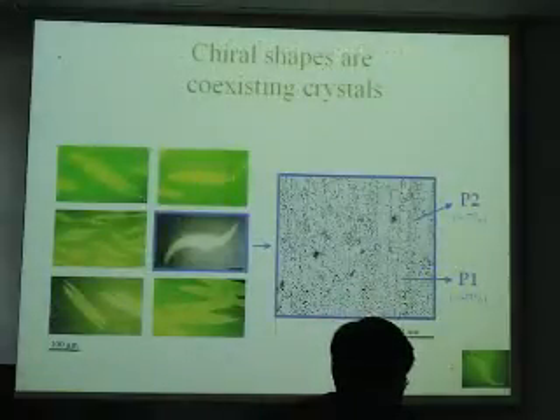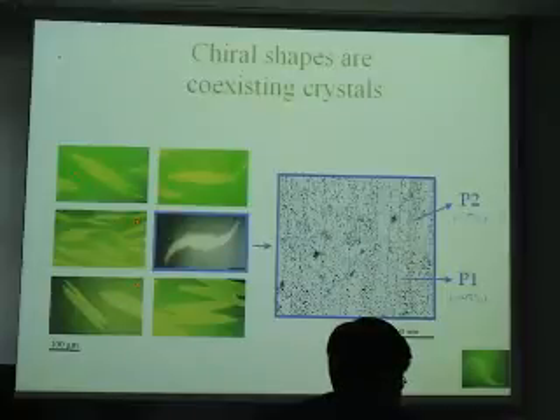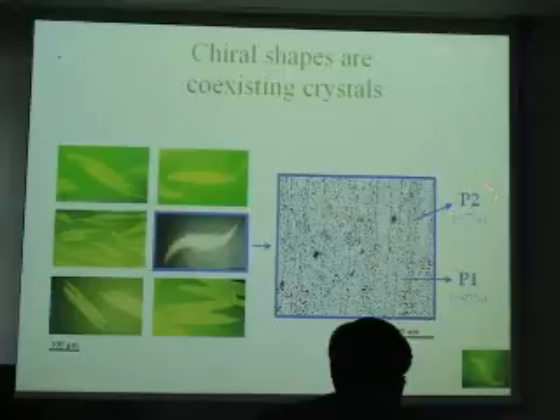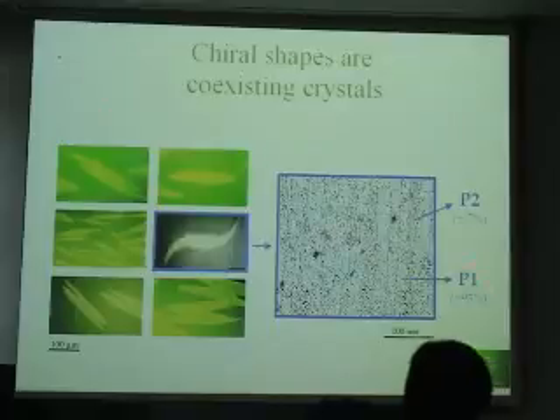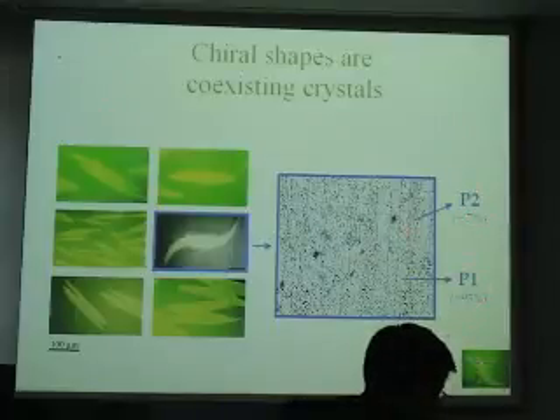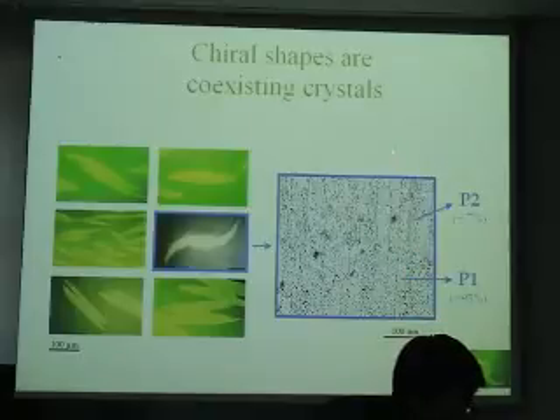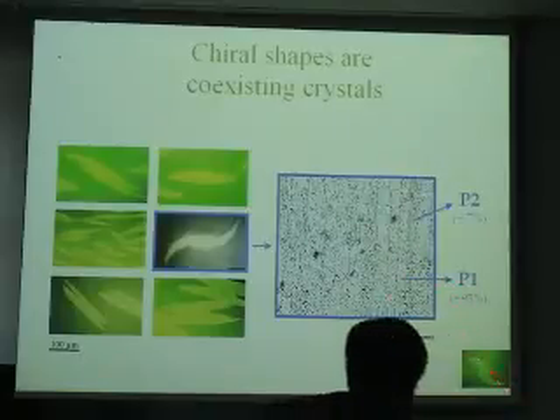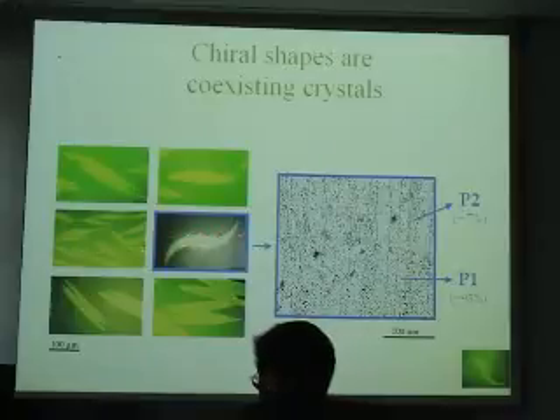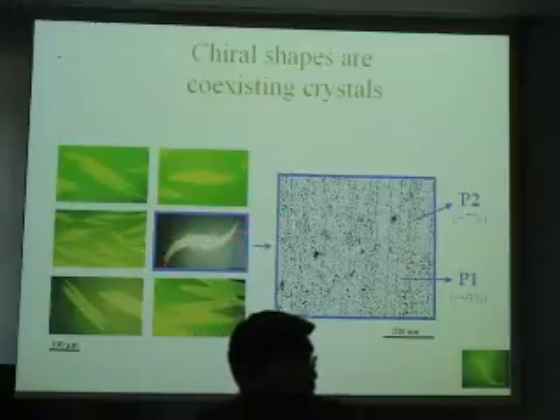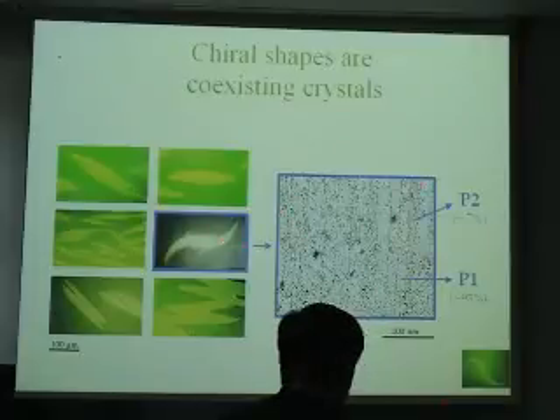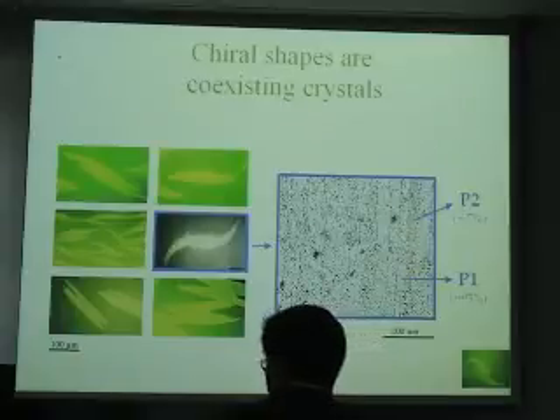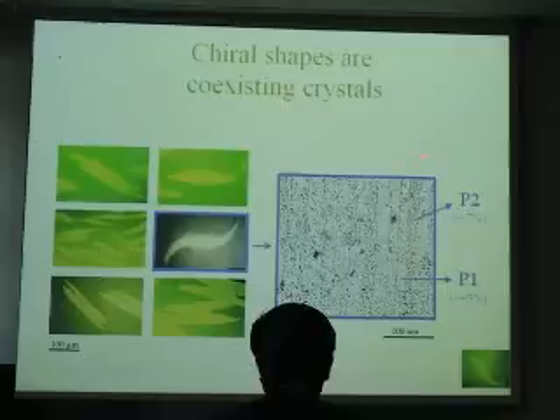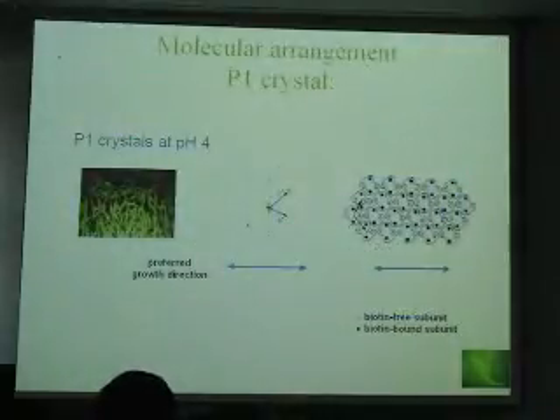Whenever we have these inverse S-shaped crystals appearing, we always have a mixture of this Tetris shape, this inverse S-shaped crystal, along with the P1 crystal. It doesn't take too many of these packing in these rows in between layers of P1 to give us this kind of a morphology. So if you look in detail at the molecular packing in these kinds of inverse S-shaped crystals, you see this kind of striped packing, and a little bit of P2 serves to give you that curvature in the morphology. This will be important later when we do our mutant studies.